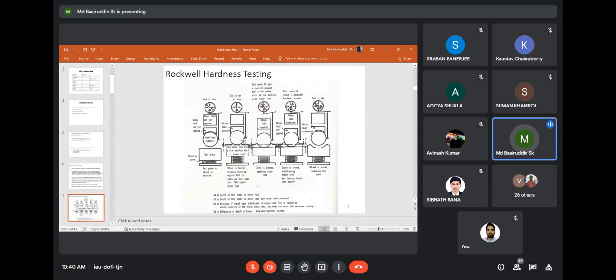now after settling that, what do we do? We try to put the major load. Major loads can be applied from 60 kilo to 100 kilo to 150 kilo. That will depend on the hardness of the test piece, okay? And then we try to measure the depth of indentation. The depth of indentation can be measured by reading the dial, okay? If we see the dial, then we will find that for different...